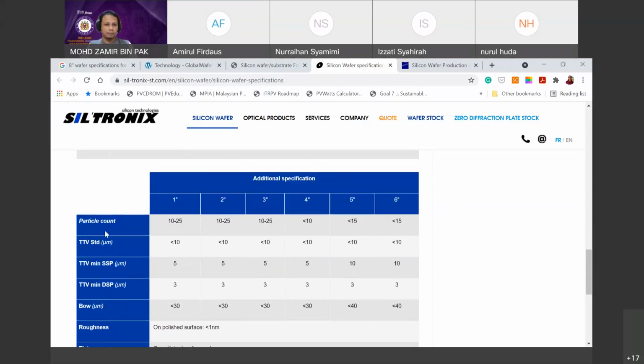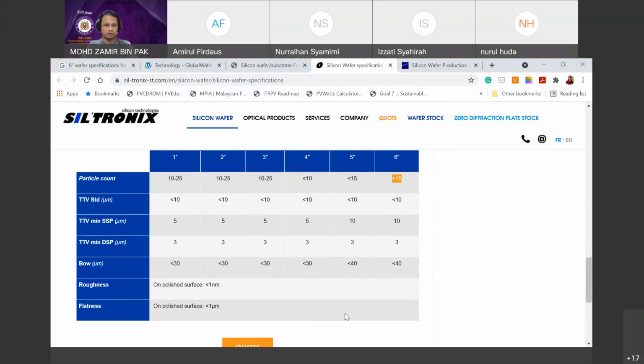So particle count. So for example, if you are choosing 6 inch, then particle count is less than 15 on the surface of the wafer. And TTV, whatever that we discussed just now, right? Total thickness variation, less than 10 micron on this thickness. So, well, they have TTV for SSP, single side polishing. So that means if you have the wafers, only single side is polished and the other side is not polished. So maksudnya, one surface is shiny and the other surface is not shiny. So if you have double side polishing, DSP, so you have both surfaces polished.